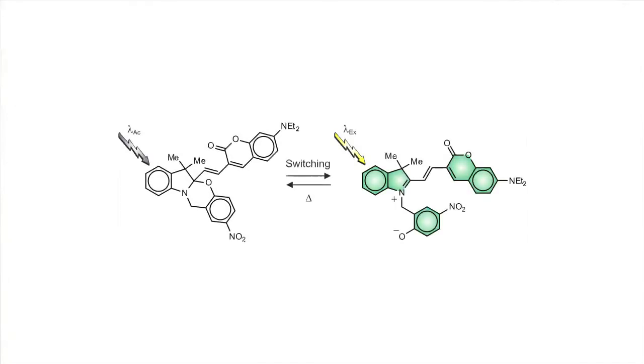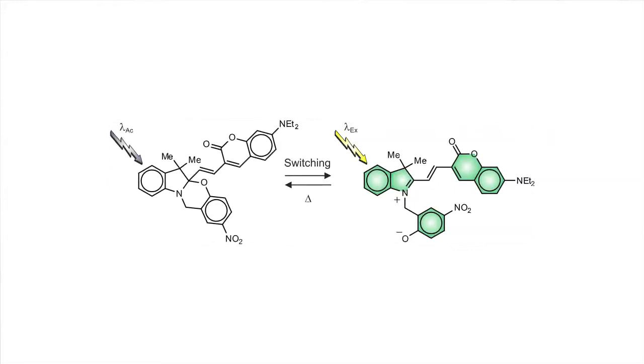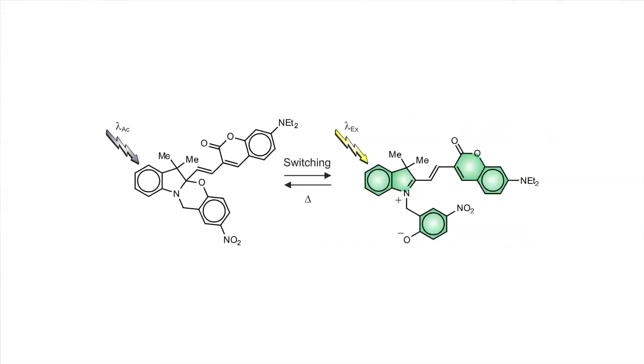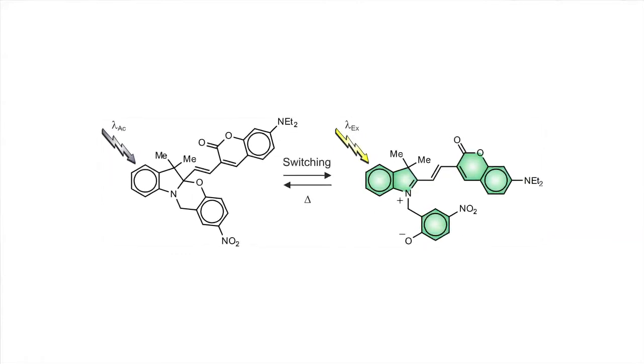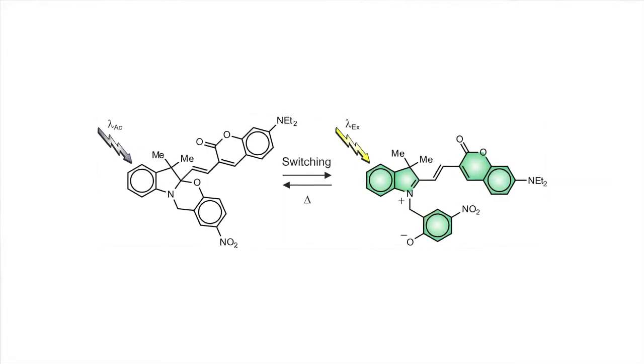We are developing photoactivatable fluorophores using fluorescent and photochromic components. We connect covalently the two components within the same molecular skeleton, and then under illumination at the right activating wavelength the photochromic component switches to a new state that affects the electronic structure of the fluorescent component and alters its ability to absorb at an exciting wavelength and therefore emit.